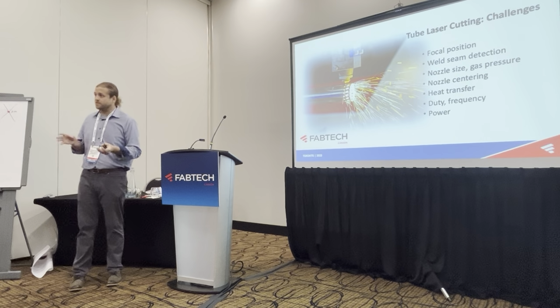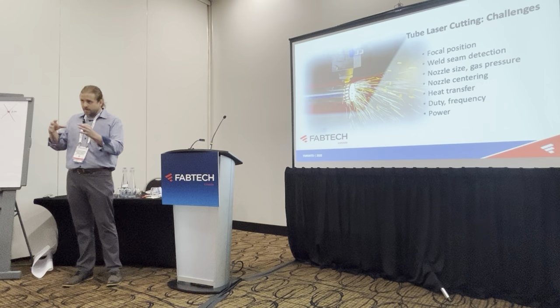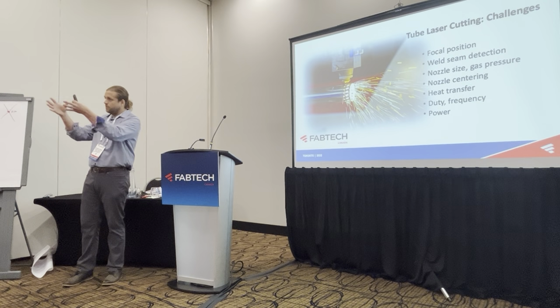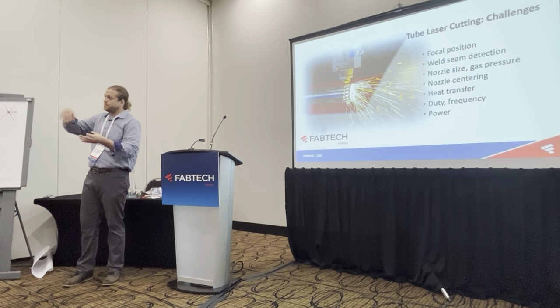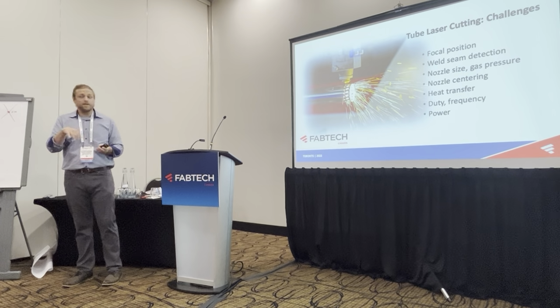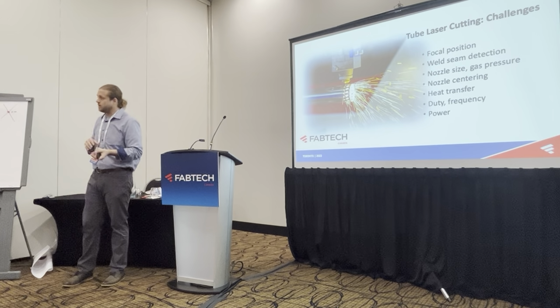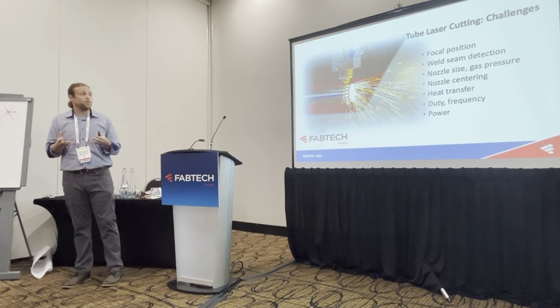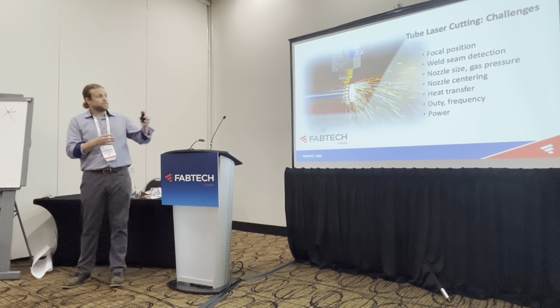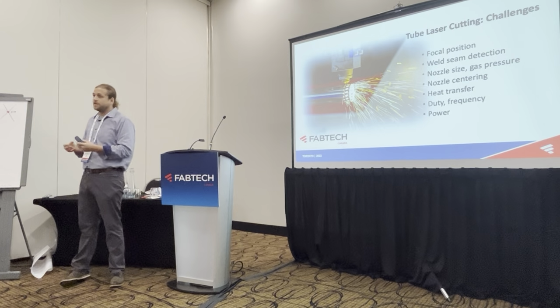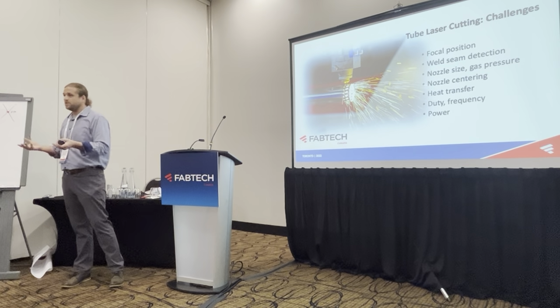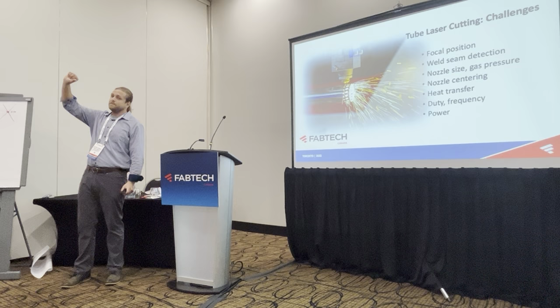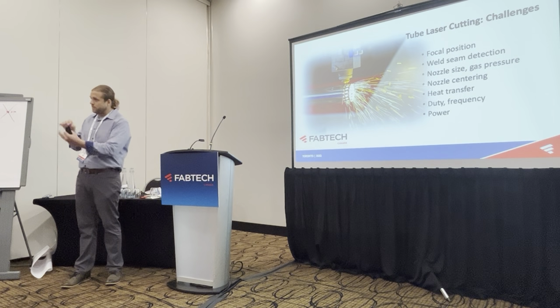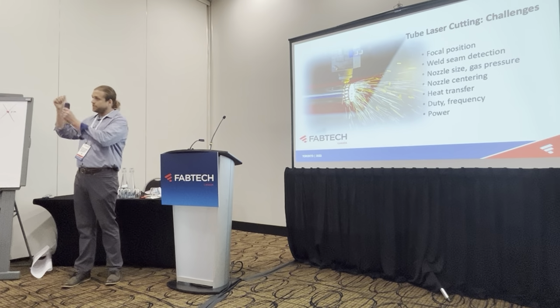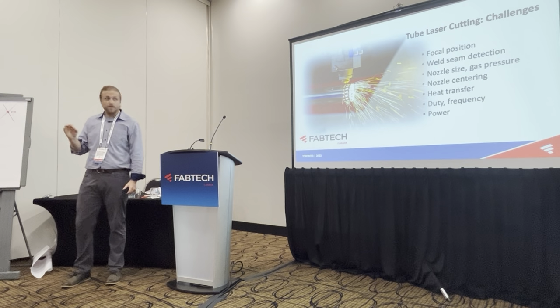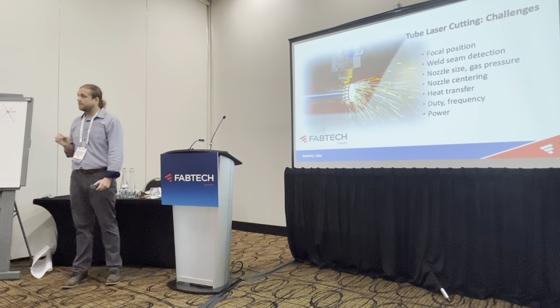Nozzle centering, that's also critical. So in any laser, there's a collimator, and in there is where you have the adjustments for the laser beam. If that laser beam is off center, now you're going to have issues with your cut quality, or it just won't cut if it's that far out of center. So what every operator has to do with every nozzle change is they really should go in and do what we like to call a tape shot, where they put tape on it, and with a scope, they then look to see how centered that nozzle is, and then they can adjust that. You want that laser beam centered on that nozzle as possible.